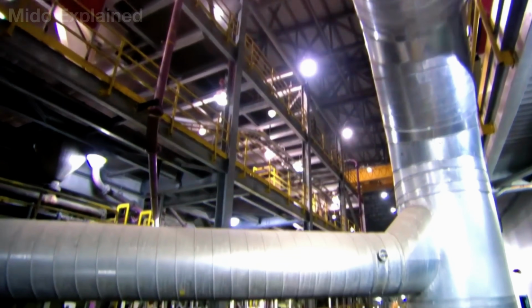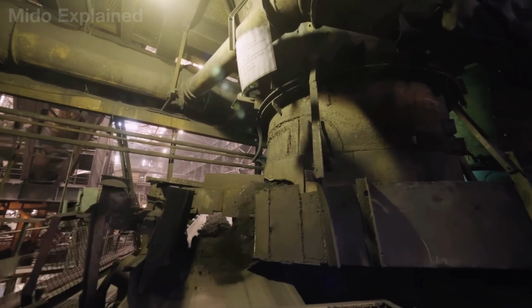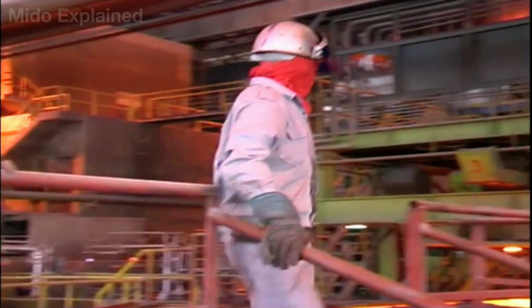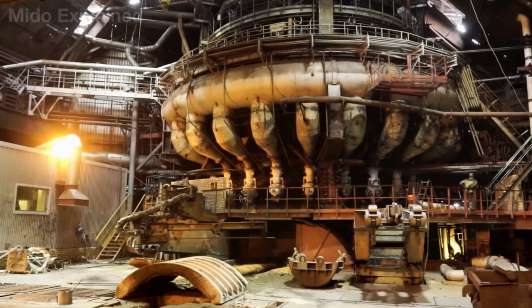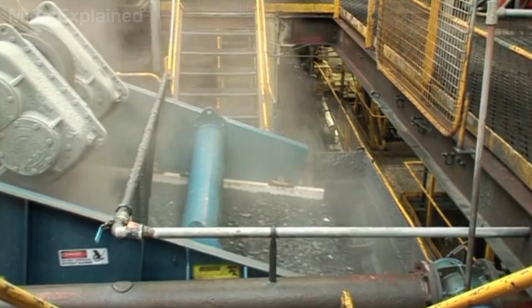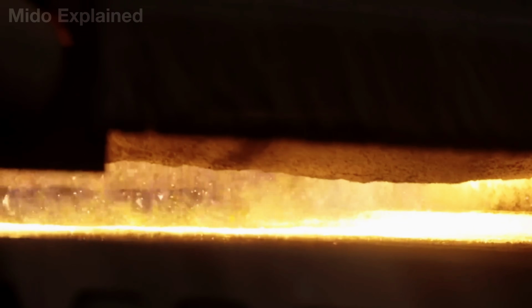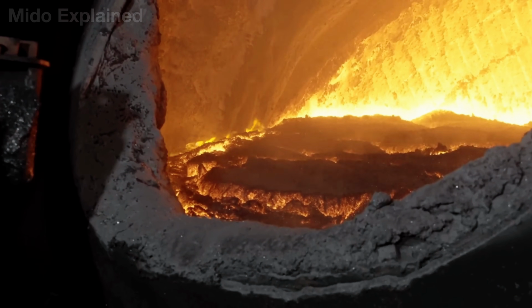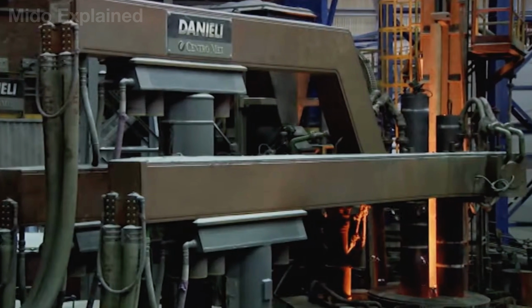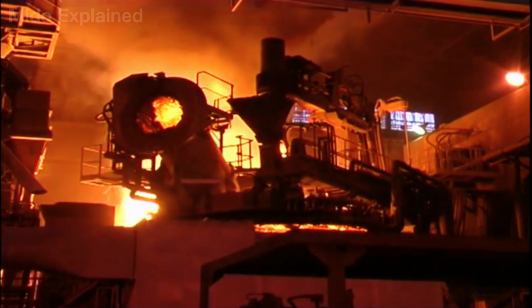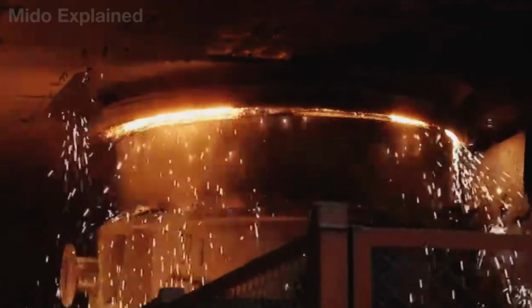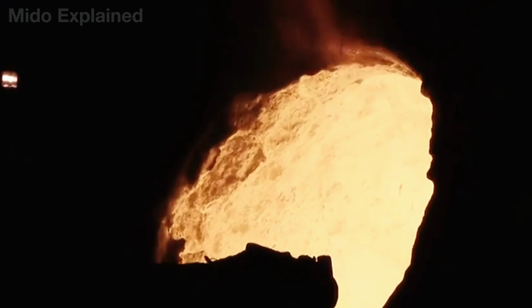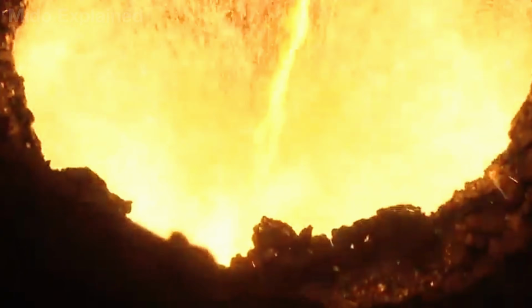After being crushed and blended, iron ore enters the most crucial stage of the entire process, steelmaking. Inside the plants, massive blast furnaces and electric arc furnaces operate at temperatures exceeding 2,900 degrees Fahrenheit, enough to transform the raw material into homogeneous molten steel. Automated control systems continuously meter the material, while sensors and analyzers monitor temperature and chemical composition in near real time. During this stage, elements such as manganese and chromium are added in precise proportions to increase the steel's hardness, wear resistance, and load-bearing capacity.